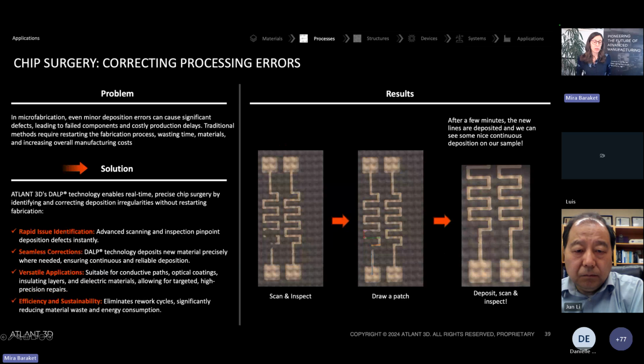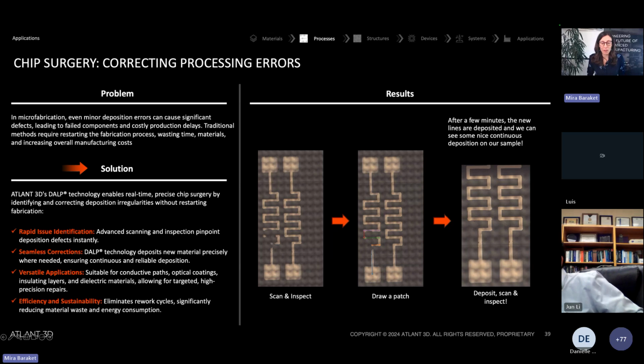So the next case here is about chip surgery, and this is very important in microfabrication, where sometimes minor deposition errors can bring significant indirect cost problems, I would say, into the microfabrication process. So in order to reduce the waste and to reduce the time, you are able with our technology to scan the surface and then inspect it. And if you see any anomalies, you can instantly draw and patch the surface. And then after your processing or the deposition, you can inspect again, and you are able to look into the surface and to create a continuous deposition. In this case, it was platinum.